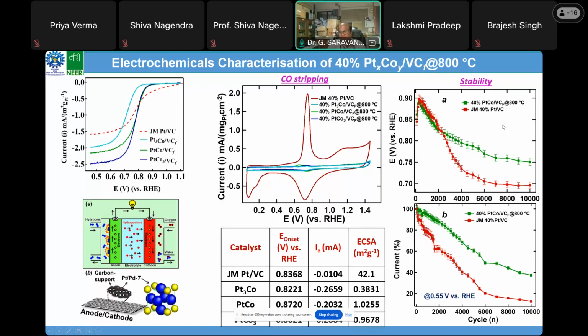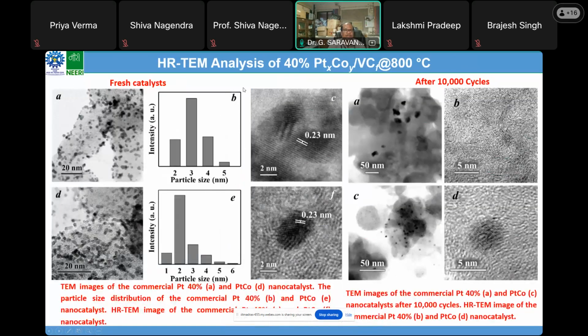So we have checked the stability of this catalyst. Of course, both catalysts show inferior activity, but when compared, the commercial Johnson-Matthey catalyst and the catalyst that we prepared in our laboratory show much better activity at any of these tested cycles. And again, we need to check the stability of the catalyst after 10,000 cycles.